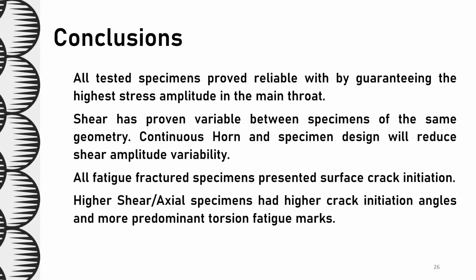this study has proven. All fatigue fracture specimens presented a surface initiation, and comparing all specimens with different shear axial ratios, we can clearly see differences between shear damage and axial damage, and in angle of crack initiation as well.